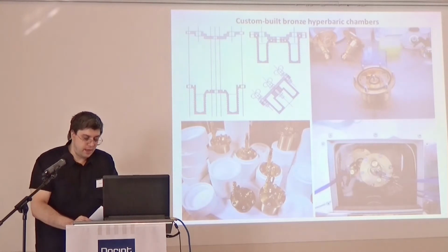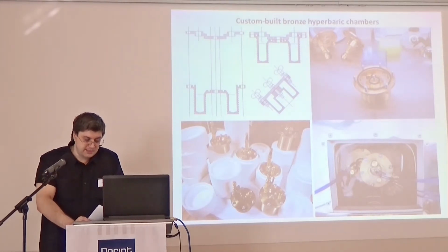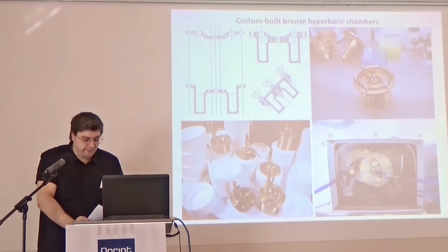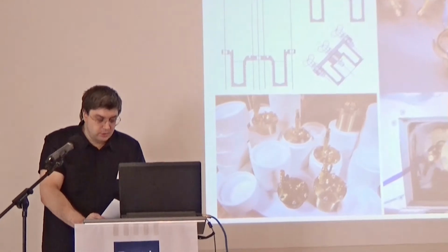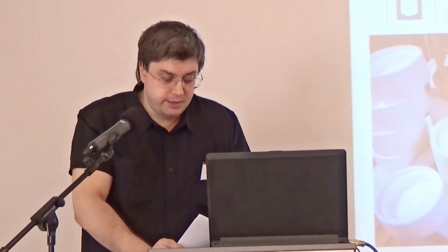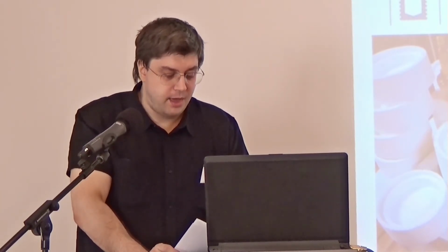As a result, it should turn out that traditional cryoprotectants, by suppressing xenon crystalline hydrate formation on the cooling stage, would allow the solution to be saturated by xenon to a significant increase of liquid viscosity, which is enough for vitrification. So this would enable vitrification using a much lesser amount of chemical cryoprotectants, and thus yield a large decrease in toxicity. We have submitted a patent application. It sounds so simple, even primitive, that I first could not believe that nobody had thought of this before.